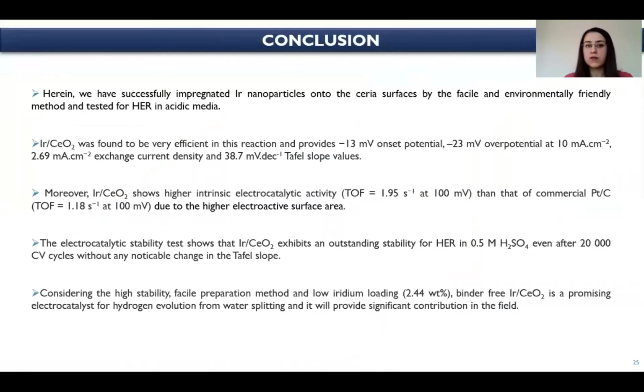To conclude, we successfully impregnated iridium nanoparticles onto the ceria surface by a facile and environment-friendly method, and we tested it for the hydrogen evolution reaction in acidic media. Iridium ceria was found to be very efficient in this reaction and provides low onset potential, low overpotential, and high exchange current density. Also, it exhibits low Tafel slopes. Moreover, iridium ceria shows higher intrinsic electrocatalytic activity than that of the commercial platinum carbon catalyst due to the higher electroactive surface area.